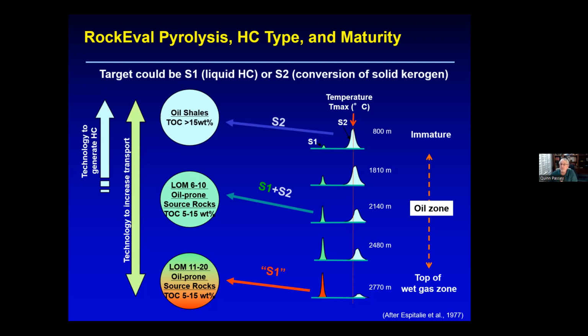And then eventually there'll be an S3 peak, which is carbonate, where they're really turning the thing into carbon dioxide, and there they can get a measure of it. If you Google Rock-Eval pyrolysis, they'll show you how you can ratio S1 to S2, and you can get a hydrogen index of it, and the oxygen index comes out of the ratio of S3 to, I believe, S2. I'm not sure.